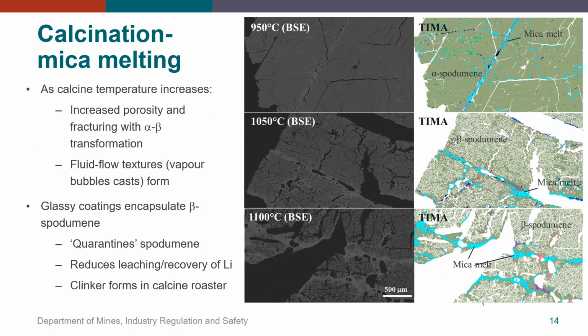This next slide shows the changes in mineral textural features associated with calcination as temperature increases. The image on the right shows backscattered image and TIMA image pairs calcined at 950, 1050, and 1100 degrees. At 950 degrees, alpha spodumene is still intact and has not yet transformed to beta spodumene. However, TIMA imaging has mapped the initial formation of mica melts in blue along a major cleavage fracture surface. As the calcine temperature increases, spodumene transformation progresses, with the spodumene becoming more fractured, porosity increases, and the formation of mica melt increases, with fluid flow textures such as vapor bubble casts also forming, as you can see here.